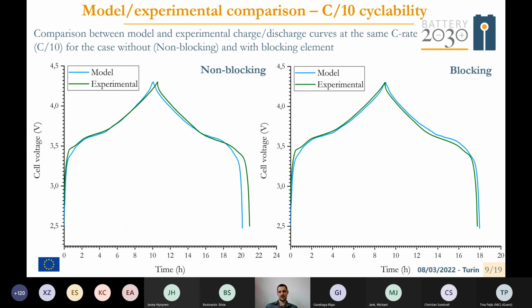Here we report the model and experimental comparison. We simulated one charge and discharge cycle at different C rates. In this slide, I present the results at C/10. We also simulated the behavior at higher C rates, and we validated the outputs of the model with experimental results from cyclability tests on the coin cell.